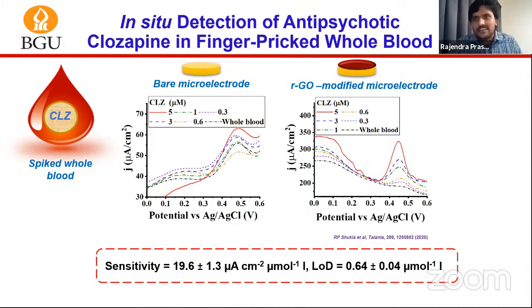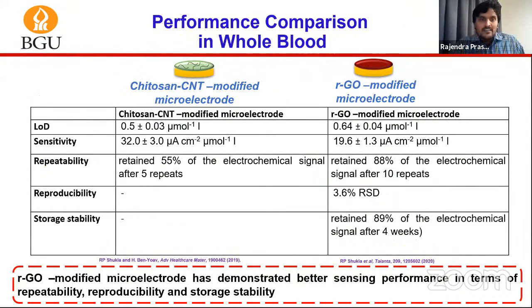We characterized it in detail, and here I'm just showing you the detection of clozapine in whole blood using the reduced graphene oxide modified microelectrode. The limit of detection is a bit higher as compared to the chitosan carbon nanotube modified microelectrode, which has 0.5, and here we have 0.6 micromole per liter. However, it has some interesting characteristics that I will show you.